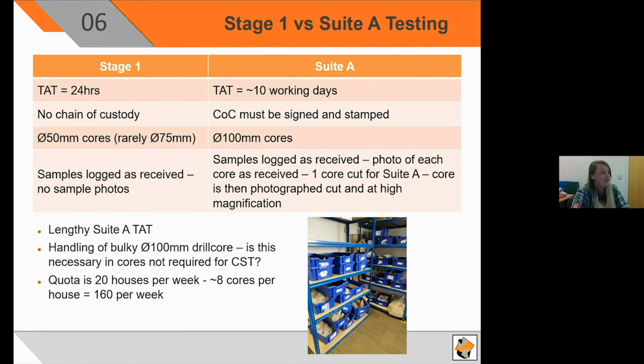So for the stage 1 test, the samples come in, they're logged in, we don't take photos of them, and we just make the estimation and visual assessment. Whereas for the suite A testing, the cores are logged in, then we take a photo of every single core we receive, then they're washed, then they're cut for suite A, the core comes back, it's then photographed again, and a high magnification image is taken.